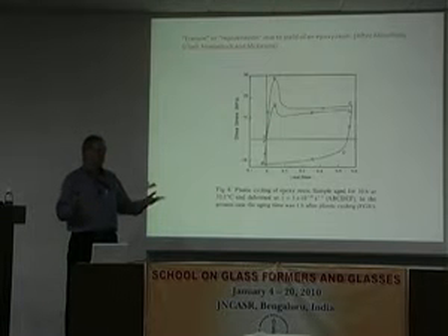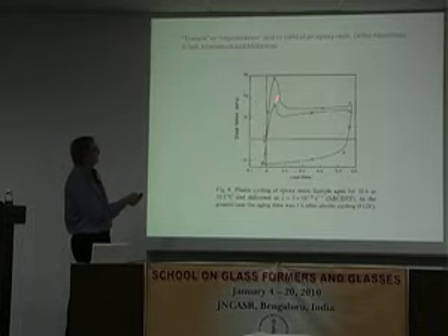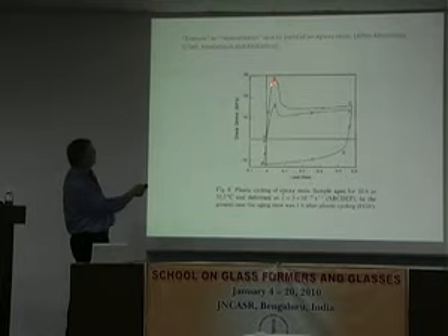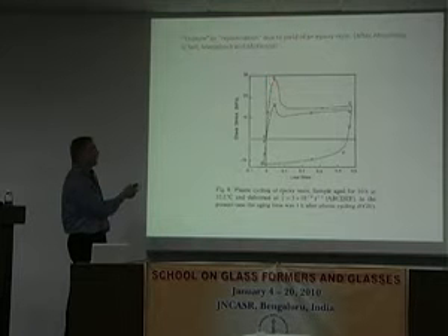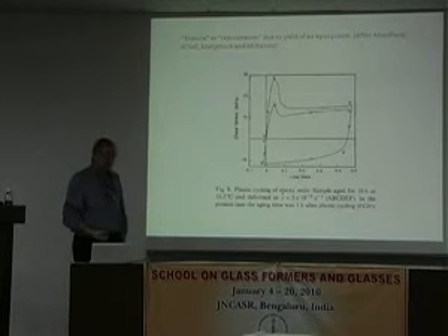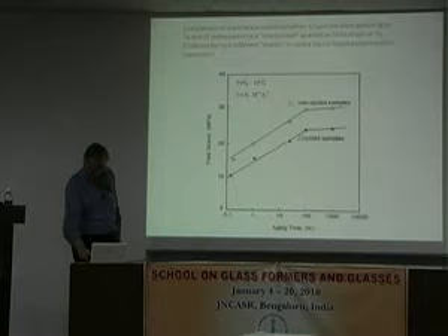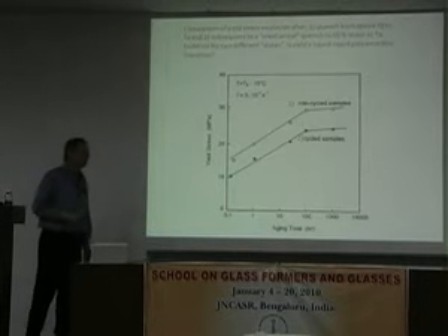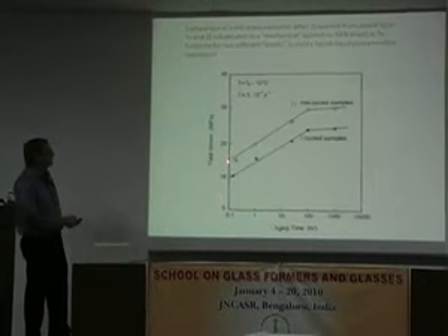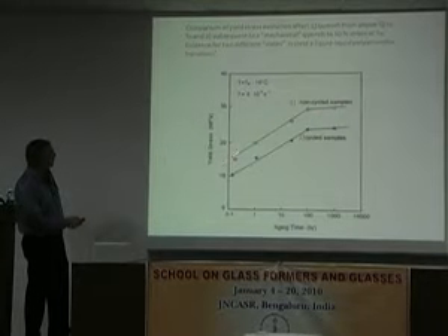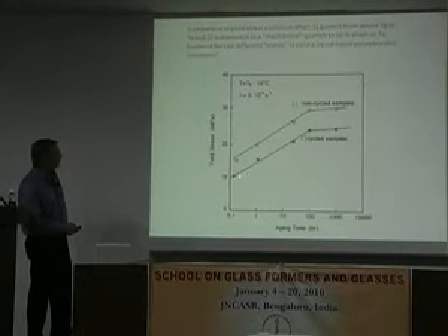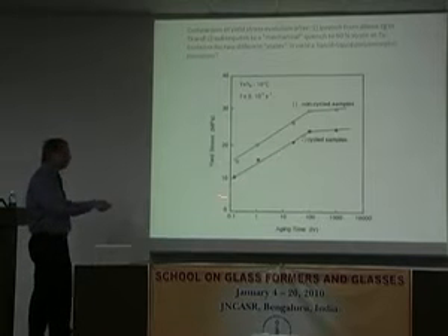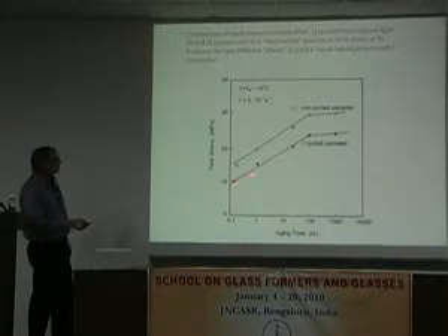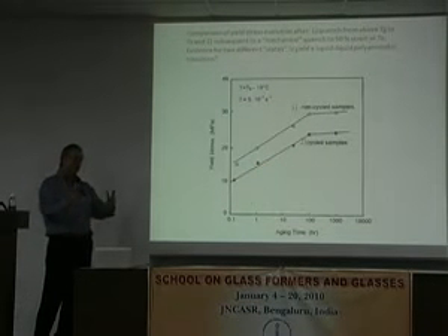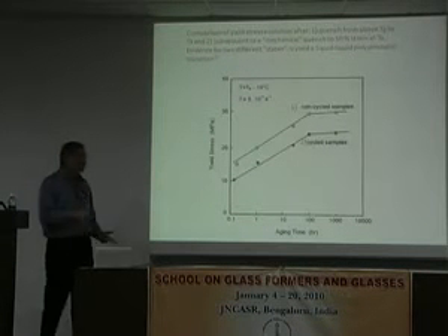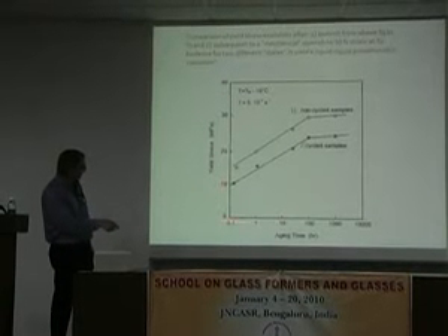Ideally, you would think that if I did a quench and this one is aged into equilibrium, it should age all the way to there as it goes back to equilibrium. And that's certainly what we expected. However, that's not what we found. What we found is the yield stress in the temperature quench sample, or what we call the non-cycled samples, versus the one where we did the cycle and then watch the yield stress go up. What we see is the rate at which it seems to recover towards wherever it's going seems to be about the same. Certainly a linear log plot it is.